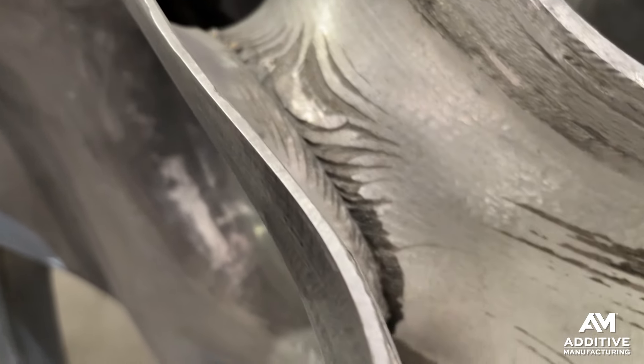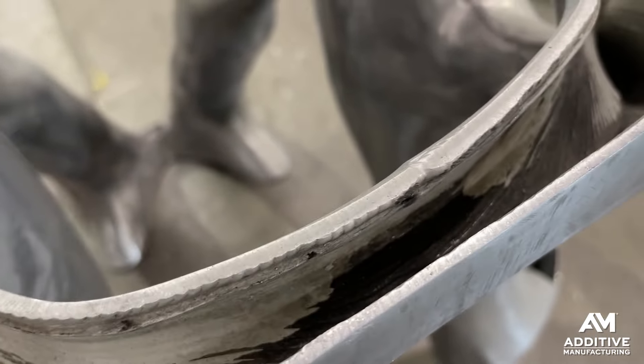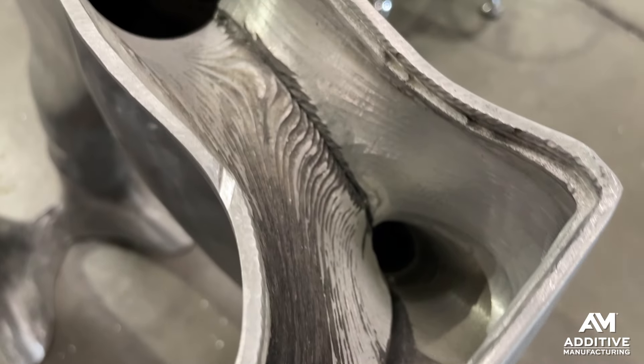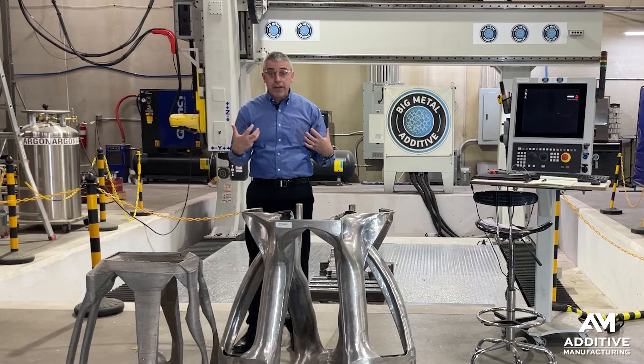The result: the wall thickness is much thinner — about a tenth of an inch versus a quarter of an inch. But these smooth walls mean no stress concentration and much longer fatigue life, significantly longer.